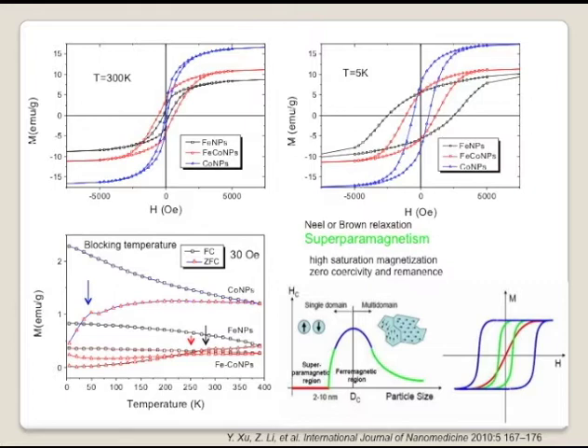Okay, it's different. How do we get the blocking temperature? We need to measure magnetization using different cooling techniques. We can always get two types of curves. One is called field cooling. It means going from room temperature to a very low temperature, here the helium temperature, 5 K. In this case, the material is cooled in a magnetic field. This is called field cooling. The other is called zero field cooling, which is cooling without a magnetic field.